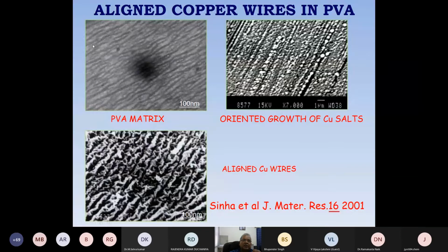Can you see my cursor moving? So you can see those PVA tubules of 5 to 10 nanometers in diameter and a few microns in length. So we were excited. We thought we were getting something like a supramolecular matrix. In the next experiment, we doped this PVA solution with a copper salt and allowed that salt to precipitate along with the gelation. Then again, we put it under the microscope, and we found that the copper salt got precipitated identically in the manner we were seeing the PVA tubules. So this copper salt precipitation had just replicated the underlying conformation of the polymer matrix.